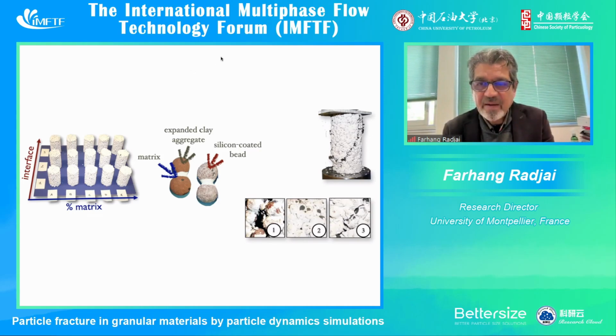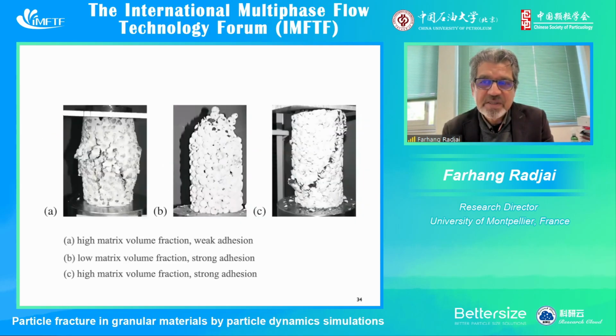And so here also we have these three types of crack propagation. Below I have shown the three possible ways the cracks propagate. And here you see different modes, fracture modes. So we have, again, these three: high matrix volume fraction, weak adhesion, that breaks like this. Low matrix volume fraction, strong adhesion like this. And high matrix volume fraction, strong adhesion, we have this type of fracture.